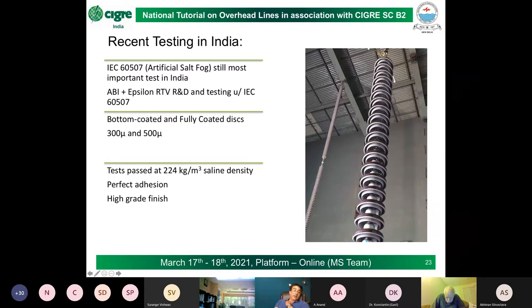In India, testing has been done. The IEC 60507 is still the most important test in India. Our friend here, I saw Sanjeev D here from Aditya Birla Insulators. He has been really instrumental in trying to push how this technology should be used. Under his guidance, we did some testing on bottom-only coated insulators and fully coated insulators, at 300 microns and at 500 microns. And amazingly, even the just bottom-coated insulators, coated at 300 microns, hit this figure of 224 kg per cubic meter saline density.